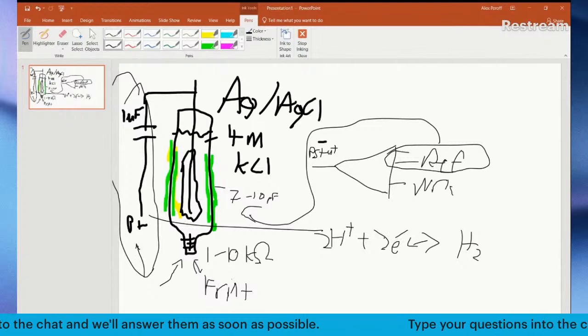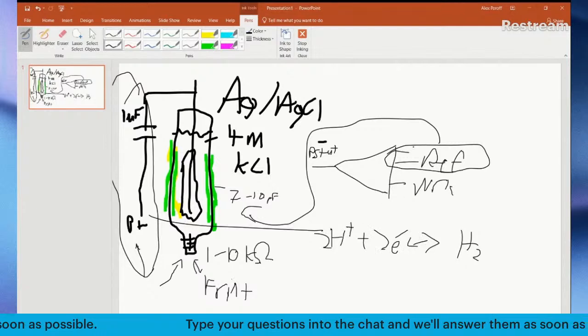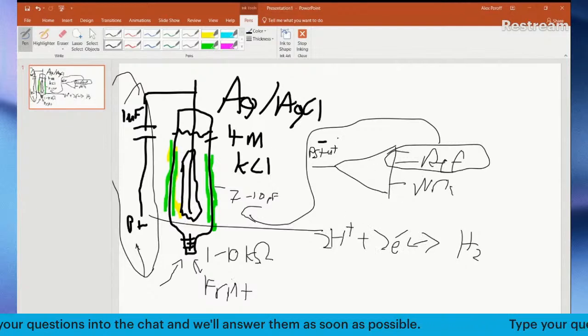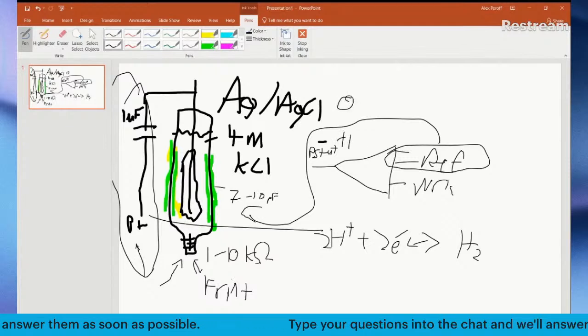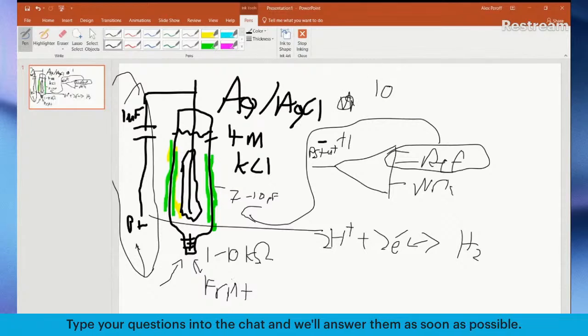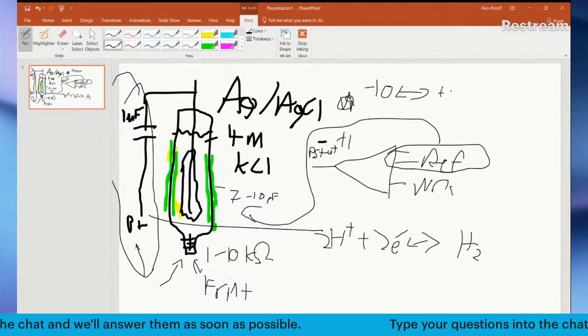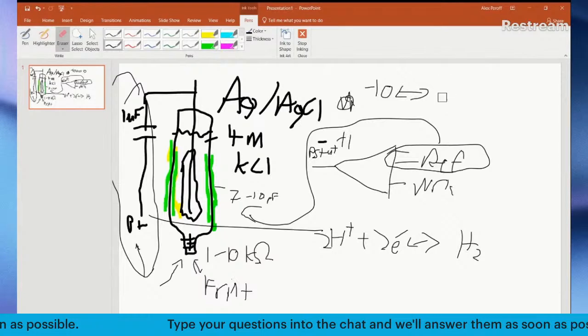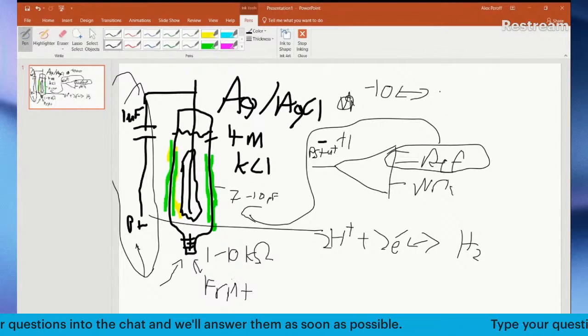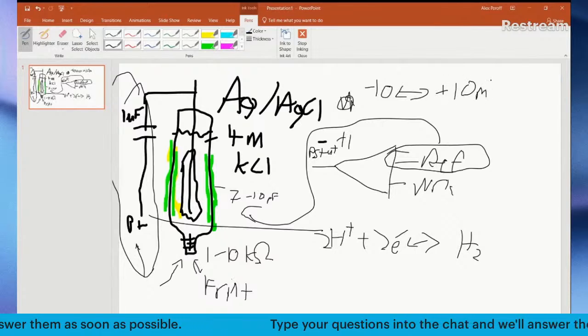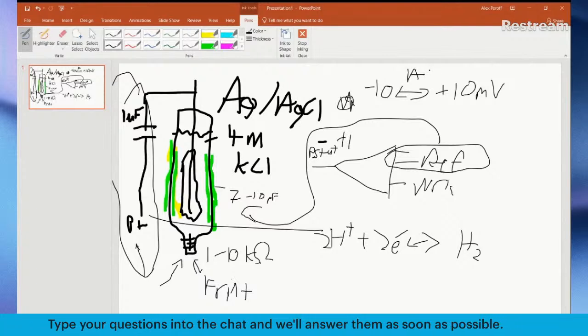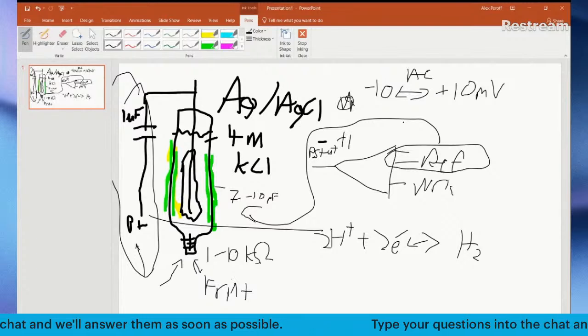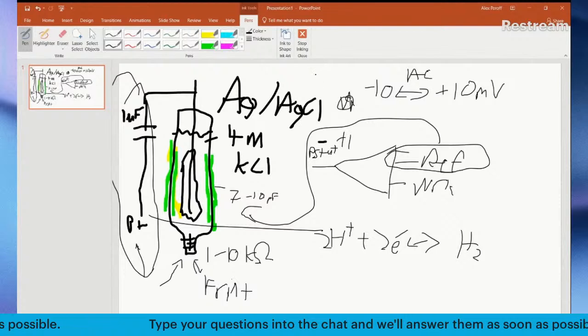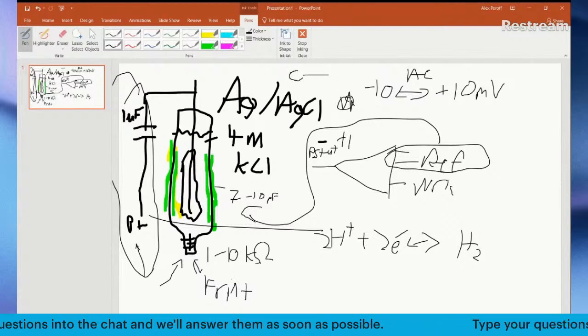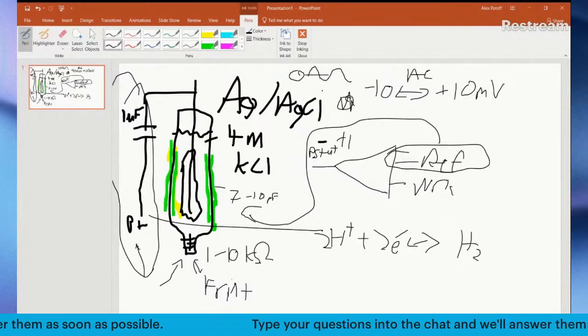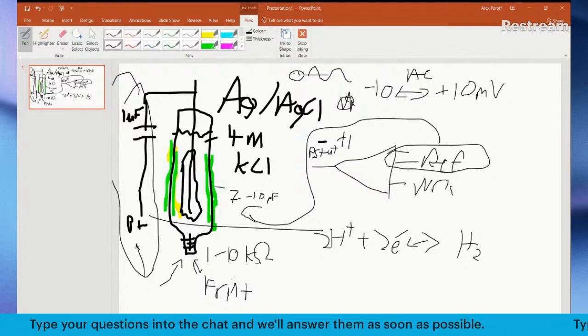You don't have the phase lag, you don't have that phase delay, but this is the potential that the potentiostat is applying with respect to. So when you tell it, I want plus 1 volt, or more specifically, you're oscillating between -10 and +10 millivolts with your AC sine wave. That's what you're really applying. That's what the potentiostat is applying, right? And that's centered around 0, right? So there's 0 and it's ±10 millivolts of the working electrode versus reference.